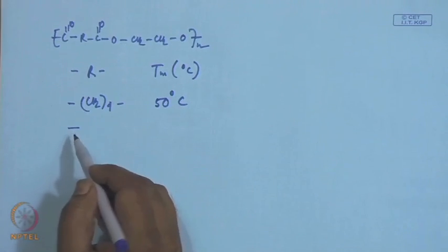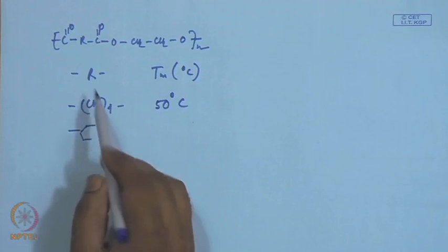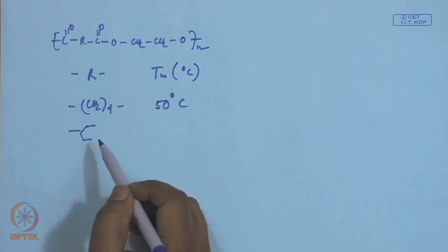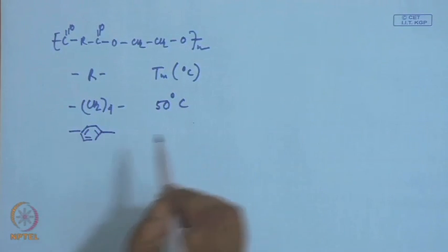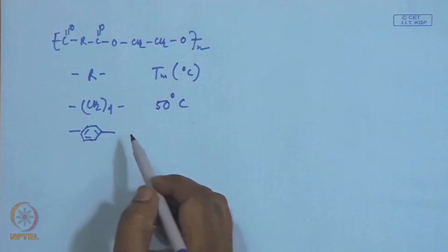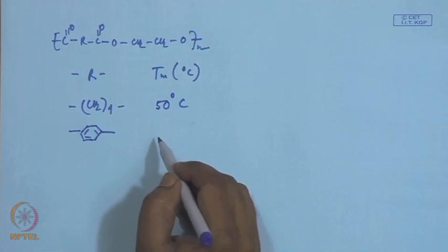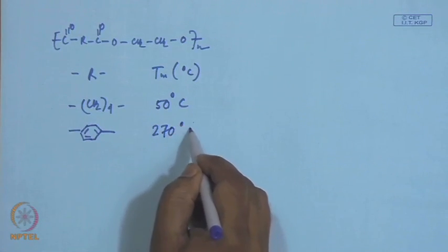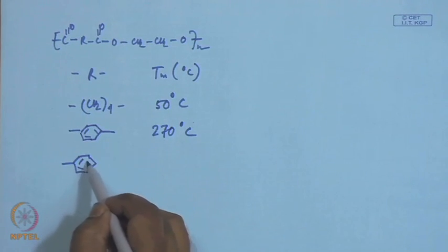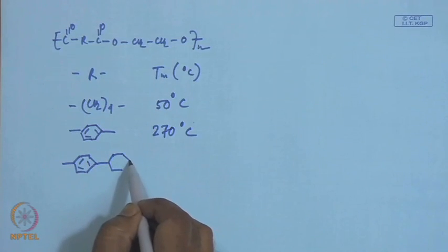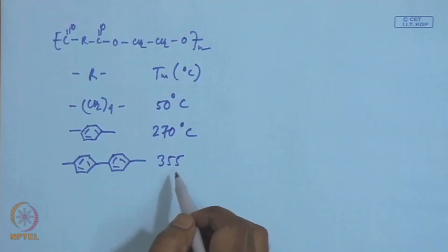If we increase to a much stiffer molecule backbone group, so we are giving an example of this backbone stiffness, which will affect the value of Tm. So, if you have a much stiffer backbone, by introducing a rigid phenyl group, the Tm goes up to 270 degree centigrade. If you have a more stiff group, then the Tm goes up even higher.